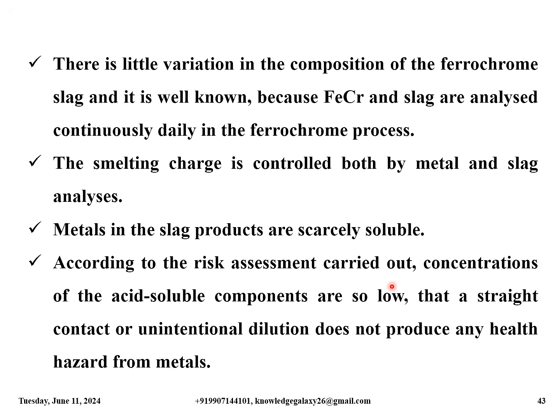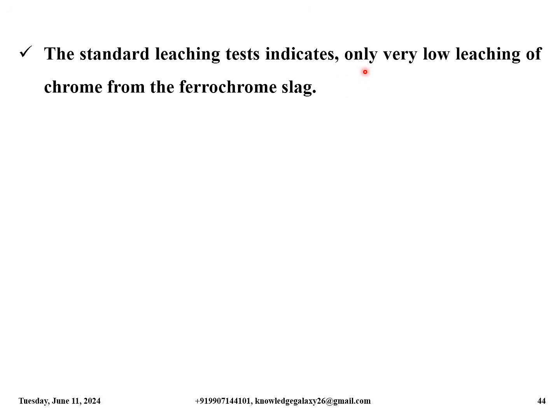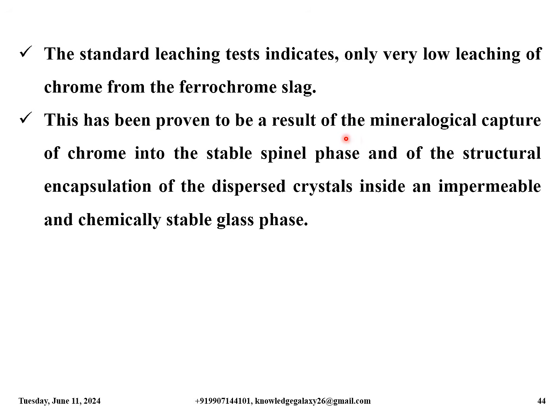According to the risk assessment carried out, concentrations of the acid-soluble components are so low that a straight contact or unintentional dilution does not produce any health hazard from metals. The standard leaching test indicates only very low leaching of chrome from the ferrochrome slag. This has been proven to be a result of the mineralogical capture of chrome into the stable spinel phase and of the structural encapsulation of the dispersed crystals inside an impermeable and chemically stable glass phase.